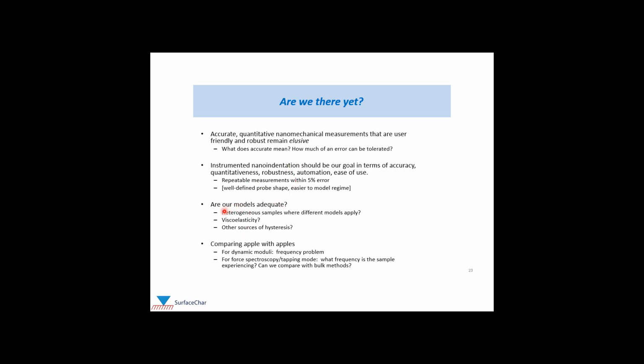And part of the problem is, as we've discussed, are our models adequate? Sometimes you may have heterogeneous samples, like I mentioned. Viscoelasticity is still a problem. There are other sources of hysteresis and dissipation in the force curves that we're not incorporating, perhaps we haven't even identified yet. And then a final problem that is particularly severe for the viscoelastic materials is comparing apples with apples. Again, you've got a frequency problem where your AFM is being done at a high frequency relative to a bulk measurement. And for spectroscopy and tapping mode types of measurements, what frequency is our sample experiencing? Is it even appropriate to compare with bulk methods? And in many cases, the answer is probably not. So I take it as good job security. We still have work to do.